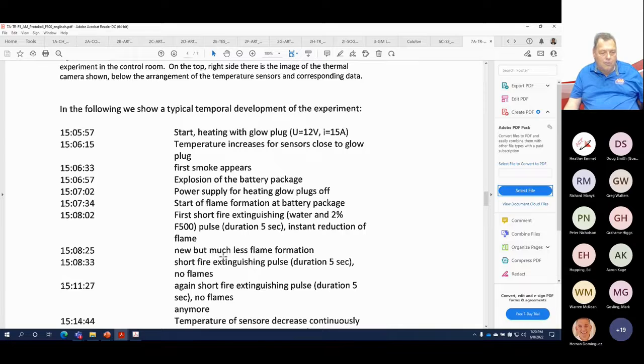So let's do a second 5-second burst. So now we do a second 5-second burst. So 10 seconds, we have no flame. Now we wait for 3 minutes. Still no flame. So from 8:33 to 11:27 is slightly under 3 minutes.